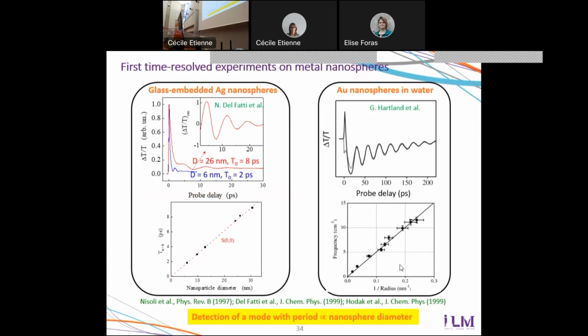Right. So now let's discuss the signals that we first measured at the end of the 90s on metal nanoparticles. Here, as I said before, the signature of vibrations are these oscillations of the signal. Here, you have signals measured with a large nanoparticle, 26 nanometer diameter, and a much smaller one, 6 nanometer diameter. You can see that the period of the oscillation is very different. And actually, this period is exactly proportional to the diameter of the nanoparticles. It was seen for nanoparticles embedded in glass, and the very same trend was observed for nanoparticles dispersed in liquids.